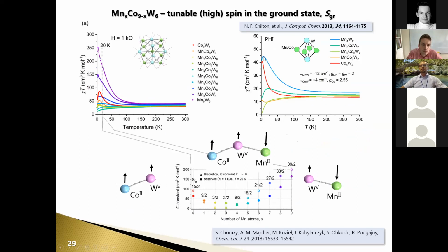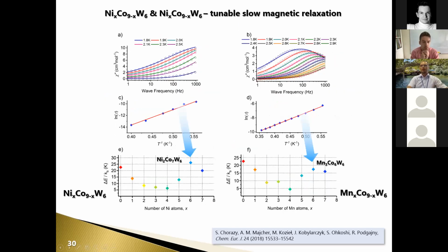And using the Phi software, we are able to shed light on possible changes depending on trimetallic composition along the smaller model, because of course of the computational time and ease. In some compositions we also obtained moderate barriers for slow magnetic relaxation, and the data are shown here.